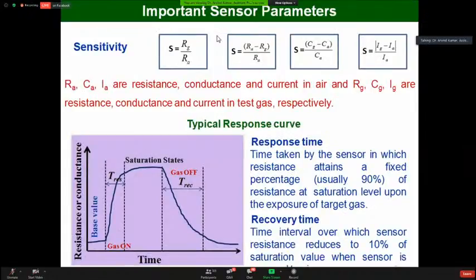There are many parameters that determine the performance of a gas sensor. First is the sensitivity. The sensitivity can be defined as the ratio of the resistance in presence of gas and the resistance in presence of air. This can be extracted from the response curve, a very important curve for gas sensors. It is nothing but a resistance versus time graph. This is the base resistance, when there is no gas, but when the gas is adsorbed at the surface, its resistance changes and it becomes saturated. When the gas is removed, it returns to its original state. So the resistance here in presence of air is Ra, and the resistance here is Rg. So Rg by Ra is the sensitivity.